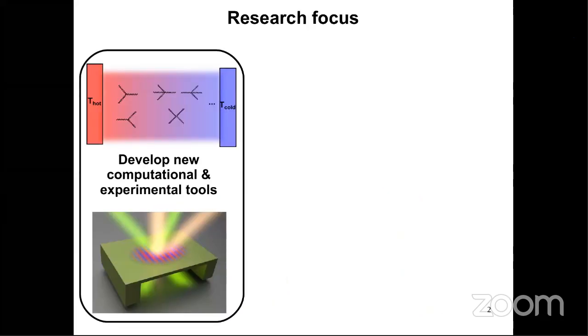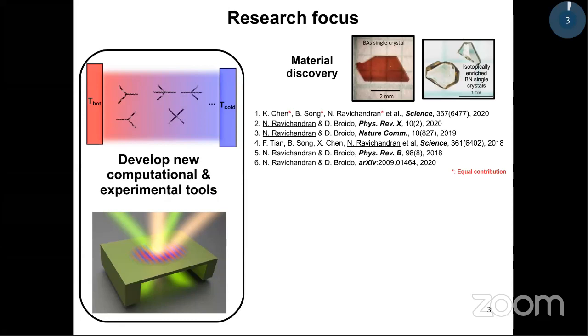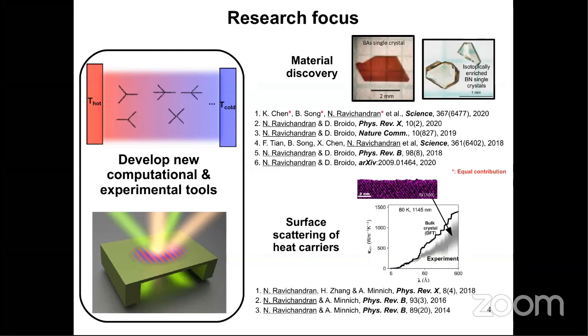So my research focus, just to give you a broad overview, is to develop new computational and experimental tools to probe the microscopic interactions among energy carriers in electrically insulating and semiconducting materials. So using these tools, I have worked on problems such as discovering new material candidates with extreme thermal properties. For example, here I'm showing a couple of pictures of new materials that we discovered using this framework. One of them is this boron arsenide single crystal. Another one is an isotopically engineered enriched form of boron nitride crystals, both of which have a thermal conductivity exceeding 1000 watt per meter Kelvin at room temperature. And I've also worked on experimentally probing interactions of heat carriers, in this case phonons, at nanoscale interfaces and boundaries. So you can find more information about these works in these papers.